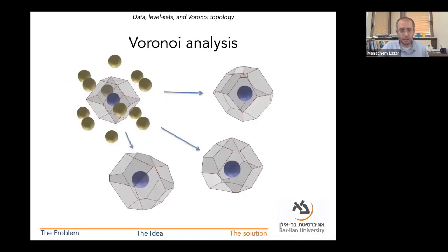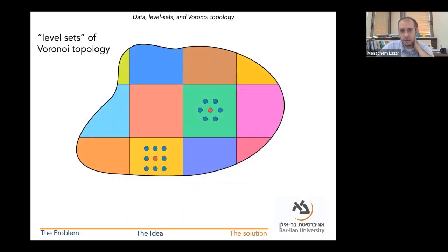So if I perturb this face-centered cubic arrangement, the Voronoi cells change and the classification changes. So suddenly you get Voronoi cells with more than 12 faces: 13, 15, 18, anywhere between 12 and 18. So how should we understand this? The truth is, I sort of fed you a lie.